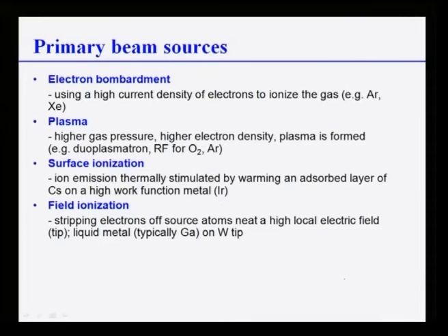You can also have something known as surface ionization. Ion emission is thermally stimulated by warming an adsorbed layer of cesium on a high work function metal like iridium. You can do that because the thermal stimulation can always lead to surface ionization.